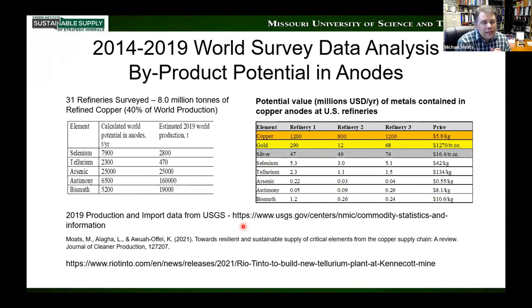So if you look at the anode composition and how much copper anode is produced in the world, and you just multiply it by the weighted average like we had before, if we were to capture 100%, which I know is not feasible, but at least it's a starting place, this is the amount of potential tonnage of each of these critical elements that you could capture just by recovering all the elements that are in the anodes. So what I'm saying is, don't change anything about mining, don't change anything about flotation, don't change anything about smelters. This is just what's available in the anode. And this is the worldwide production according to USGS.